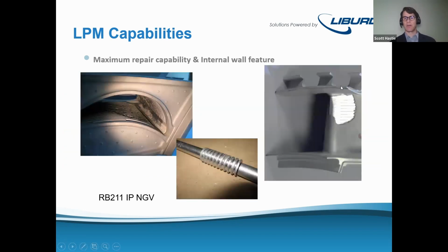Some other things that we get involved in, this is just the casting that we talked about. Sometimes there's some internal rib damage. The internal geometry of these parts must be at the correct temperature for type 1 or type 2 hot corrosion, and we get a buildup of the deposit. And certainly we know that we have to remove that deposit, otherwise it will just continue to eat through the wall thickness of the part.